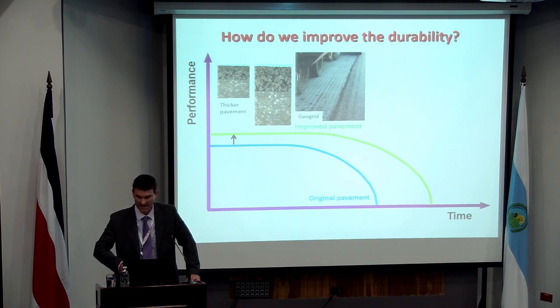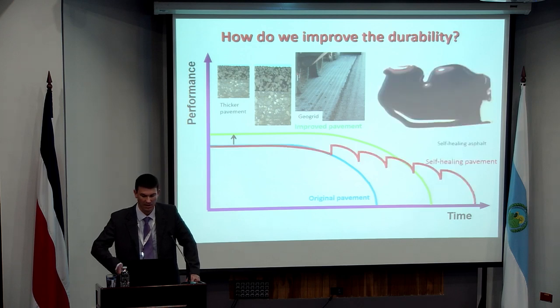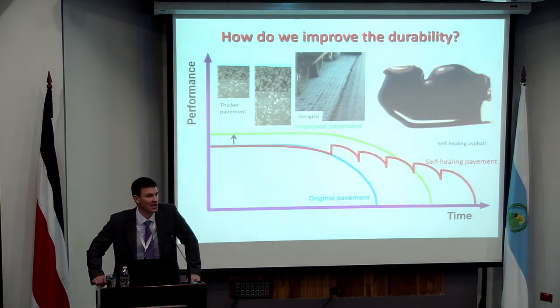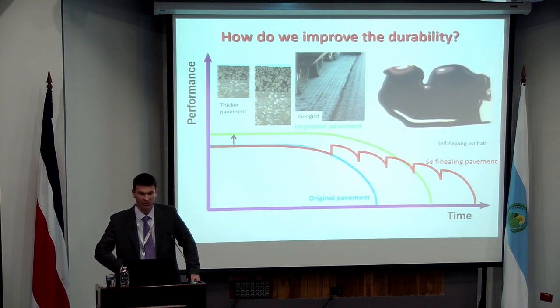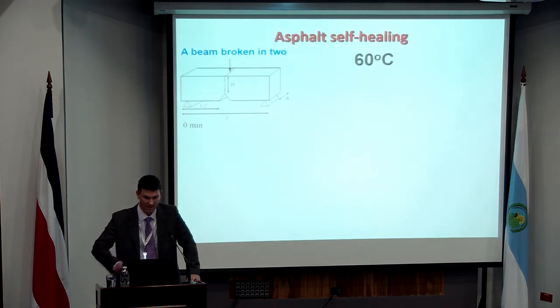So what we've looked at is saying, well, let's not change the initial behavior or the initial performance level. Let's just allow the material to get to a particular degree of degradation or damage and then effectively heal itself, and try to get back to maybe not its starting point, but at least to something that's better than what it was when it got to the point where it was deteriorating. And that's the approach that we've looked at in terms of our self-healing pavements or self-healing asphalt.